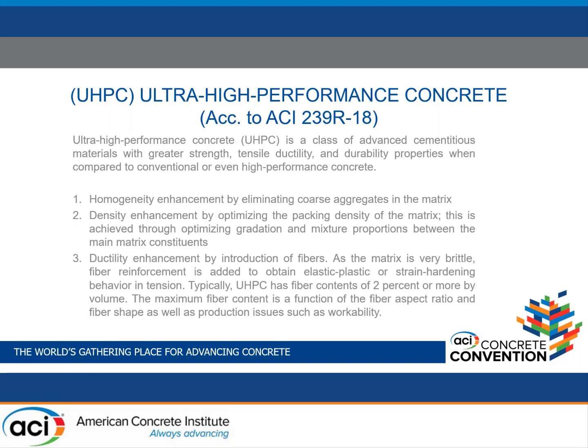But in our case, we did not introduce fibers into the matrix. We added glass and carbon fabrics, and we increased a little bit of ductility by introduction of these fabrics instead of introducing fibers here. So I have to say here that increasing ductility a little bit with using fabrics might be valid only for thin materials.